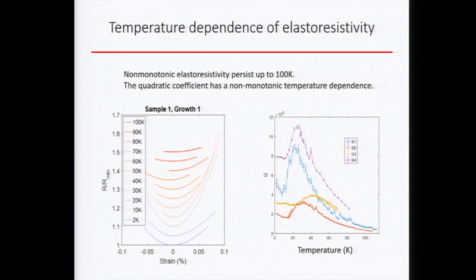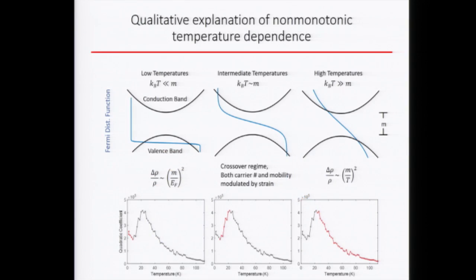So you should expect some crossover from the Fermi energy quantum degenerate regime to a thermally excited regime. Therefore, we track this quadratic dependence as a function of temperature, and you measure the coefficient as a function of temperature, and you see this very non-monotonic temperature dependence. It first goes down, then going back up, and then going back down. Initially we were a bit puzzled, and they're all consistently showing this behavior. But later on, when you actually do the Boltzmann transport calculation, it actually makes sense.